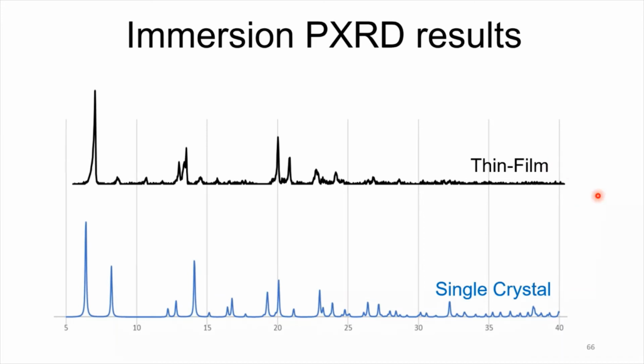And as I was mentioning, this didn't work as well as we wanted. You can determine it is the same MOF, even though there are still some extra peaks in there. You can determine it is the same material. But one characteristic of thin films that you can determine through XRD is the disappearance of some peaks.